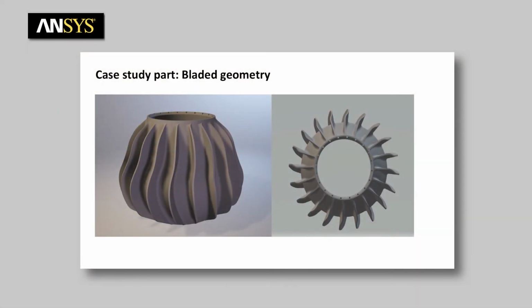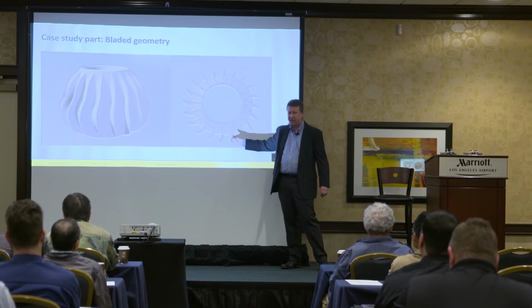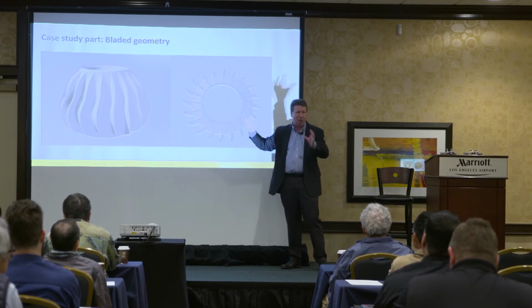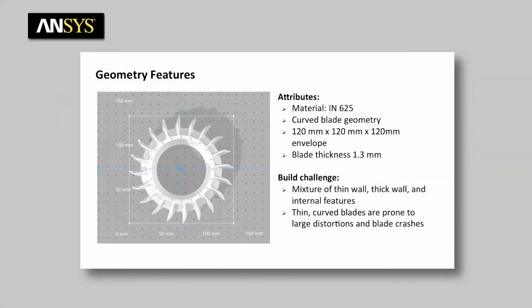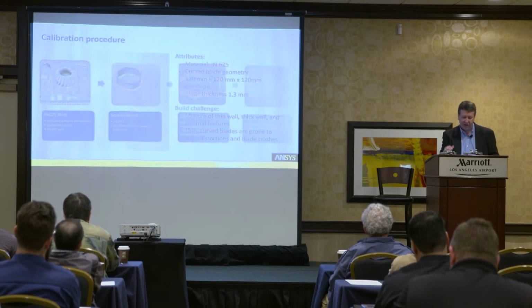This is a classic, very difficult to build accurately geometry because it's got a bunch of thin walls, but also some thick to thin transitions. Those are always problems. You've got some internal passageways, and this is the type of curvature that, if you don't support it, is going to warp all over the place. The material we built it out of is Inconel 625. It's about 120 millimeters in each dimension. The blade thickness is about 1.3 millimeters, so relatively thin blades. And so we wanted to see what was going to happen.